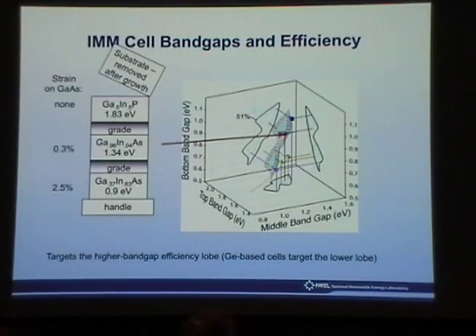And so that was a junction with one metamorphic junction. That was the blue one. And in fact, we've gone further. We've made cells with two metamorphic junctions. So here, all three of the band gaps have been reduced from their original one. So you grow it here, start down this way, and then flip it over. So here's 0.9 eV, 1.34 eV, 1.83 eV. That's at this red point, which is at the bottom of that lobe.